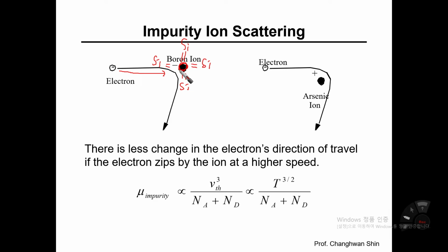So once a boron atom is well electrically activated into the crystalline material, then it's going to be ionized so that charged particles such as electrons and holes are traveling, and once they are getting closer and closer, the trace and direction of a charged carrier such as electrons or holes will be varied. Okay, so this scattering event can happen because of the ionized impurity atom.